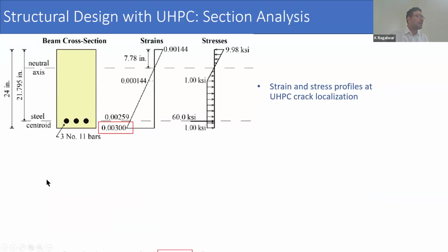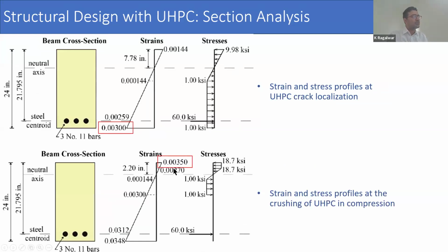9.98. And the last value we will calculate to build our moment curvature plot is equating extreme compression fiber strain equal to crushing strain. So at this point, we will see finally we can have the bilinear model in compression. However, the stress localization occurs much above the extreme or the bottommost fiber. So therefore, we have stress block extending under tension up to only a partial point. And then, of course, we have the contribution from steel.